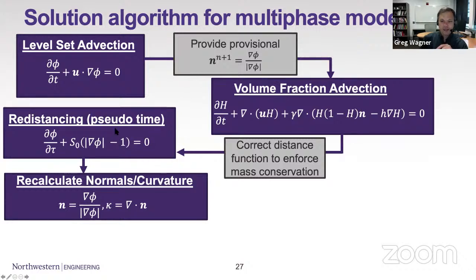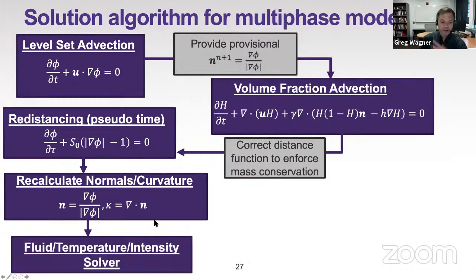Then we use that updated volume fraction to redistance our level set, and we end up with a recalculated normal vector at each point. And those are the normal vectors that we can use in order to compute things like surface tension and the evaporation forces in our thermal and fluids problem. So finally, we solve for the fluid temperature.